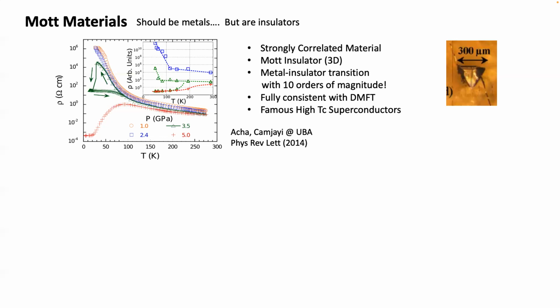So you see here very clear insulating behavior and here very clear metallic behavior. But the thing that I want to emphasize most is how it goes from insulator to metal. It goes through a first order transition with very strong first order character, and you see the hysteresis loop there. And this, of course, is fully consistent with my other bread and butter of every day, which is dynamical mean field theory, which predicted this metal insulator transition in the 90s, actually during my PhD work. And this is, to me, still the most beautiful demonstration of that. This material doesn't order or anything. It's three-dimensional, has a frustrated lattice, et cetera.